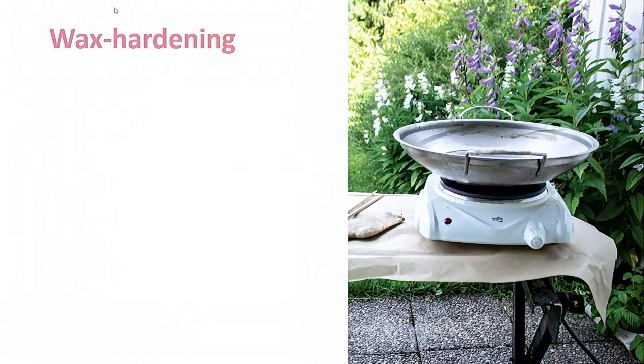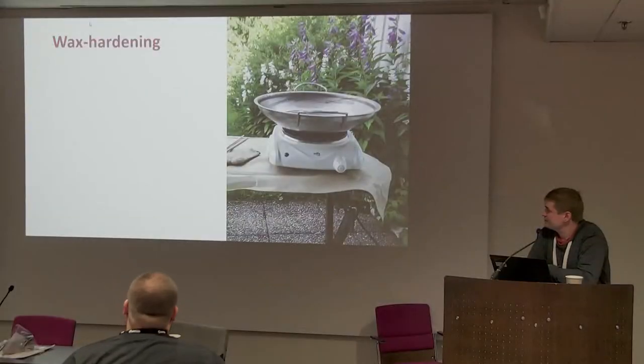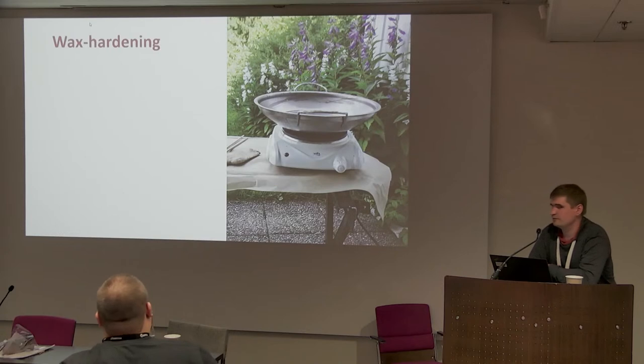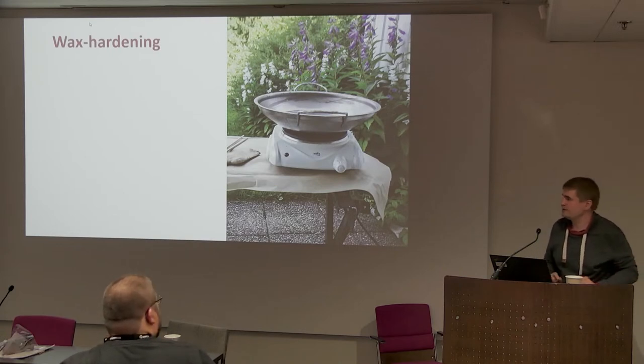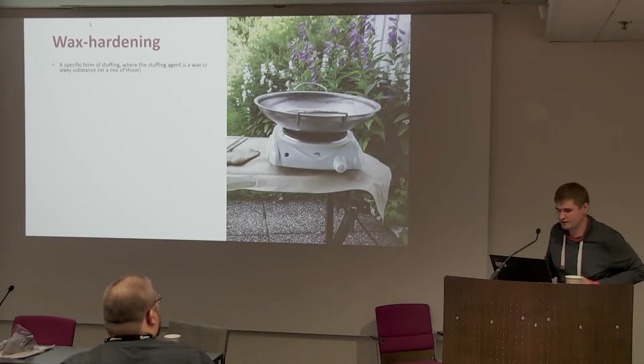So wax hardening, basically we immerse the leather when it's completely dry. Do not try this if it's not dried, you will get nasty results. So you have completely dry leather, you have wet formed it into a shape, then you dry it, then you immerse it in a hot wax, so you impregnate the material with it.